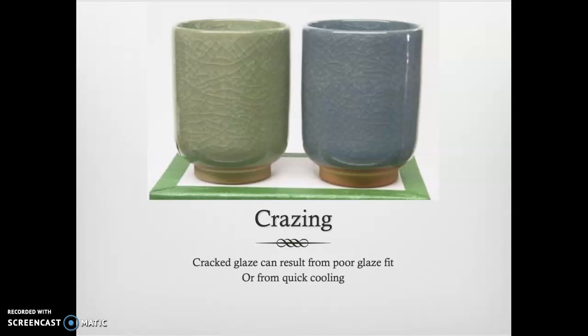That cracked glaze, what's happened is, for some reason, the clay has shrunk less or more slowly than the glaze has. And so as the glaze shrinks, because it was 1800 degrees or 2300 degrees or however hot it was in the hottest time in the kiln, as it cools down, the clay and the glaze have to cool. If they don't cool at the same rate, then that glaze can crack. And in bad cases, it can crack off. So we call that crazing, or shivering sometimes, when it actually falls off. It cracks so much that it's gone.